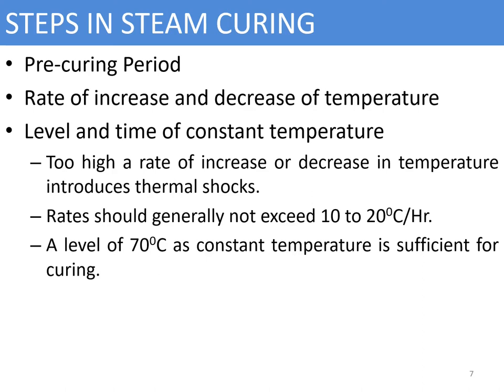The required temperature depends on the percentage of strength you want to achieve compared to the 28-day strength. At lower temperatures you may still achieve the required strength, so trials need to be conducted at different temperatures to determine the optimum temperature at which the required strength is achieved so that subsequent activities can be carried out.